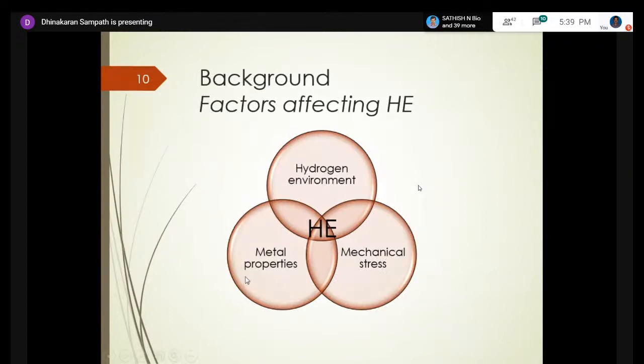So for factors affecting this, we need all three components: hydrogen environment, material properties, and mechanical stress. Here, high strength alloys are very deleterious. Also, if we have phases in the grain boundary, that is detrimental too, as it will promote grain boundary cracking, intergranular cracking. And mechanical stress, again, is very important, either sustained or fatigue loading. And the hydrogen environment could be electrochemical based or gaseous based. So all of these environmental parameters play a role in the susceptibility of a material.